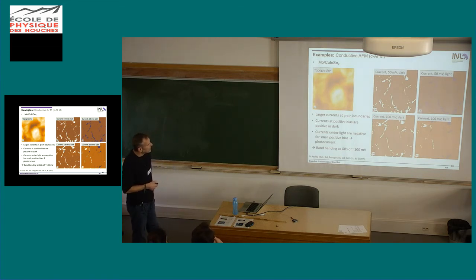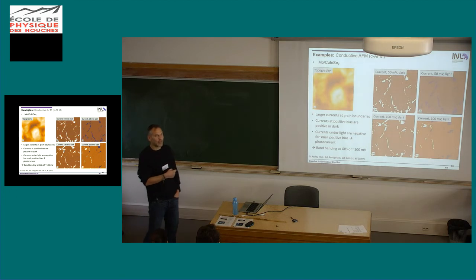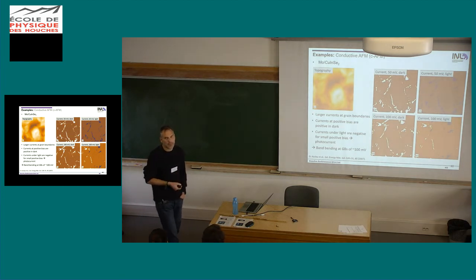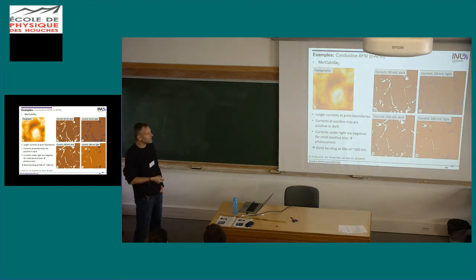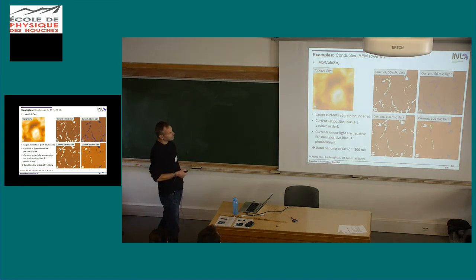However, if they shine light, then for the small bias, what they observe is that the current turns around. So suddenly the current actually flows in the other direction. And the reason is this is a photocurrent. So this is a solar cell material. So these are photocurrents that we see here, and they are in the same positions in the same grain boundaries.